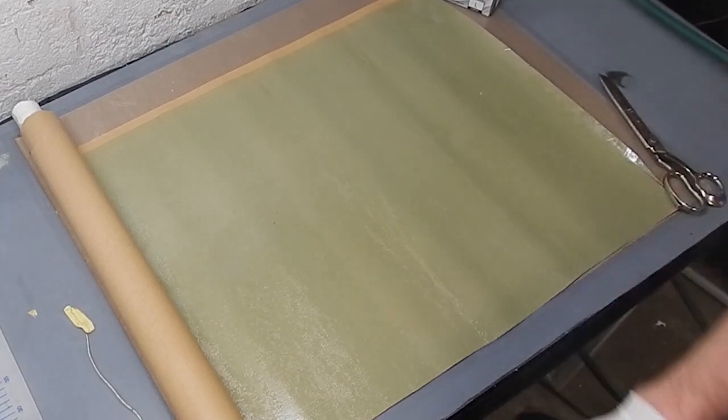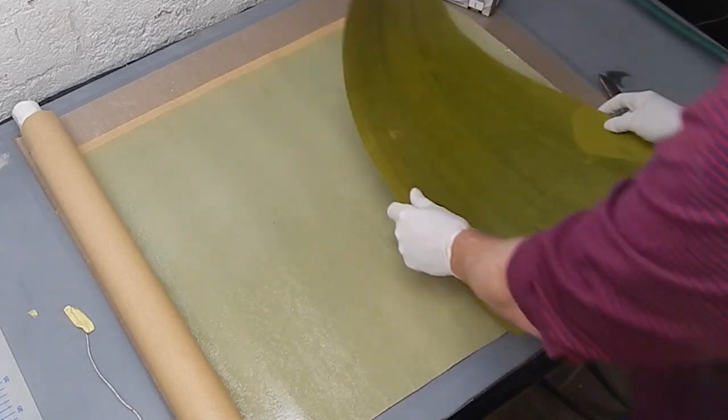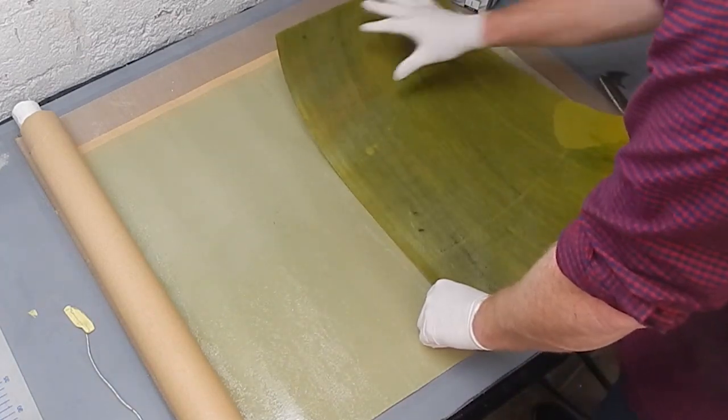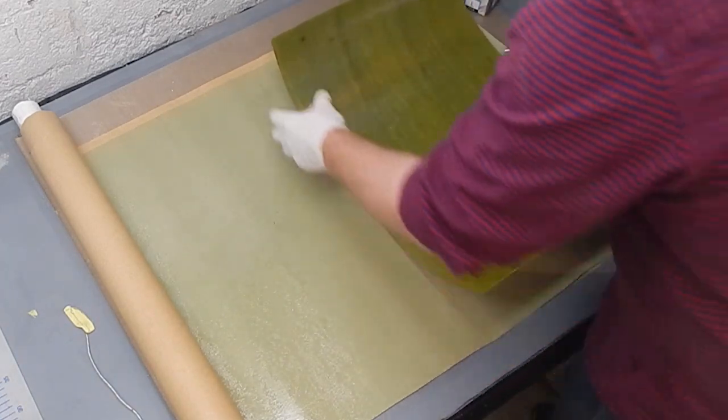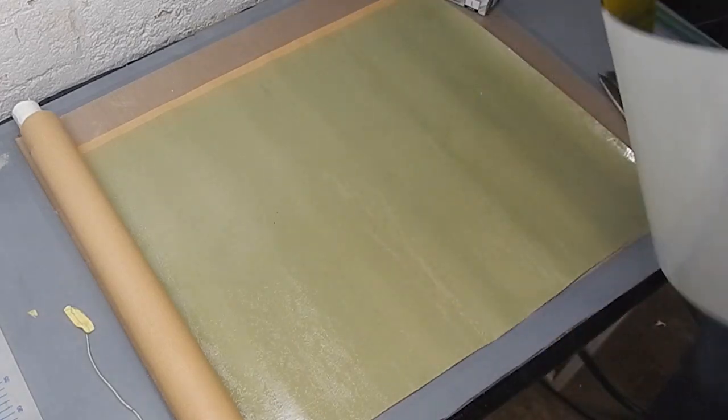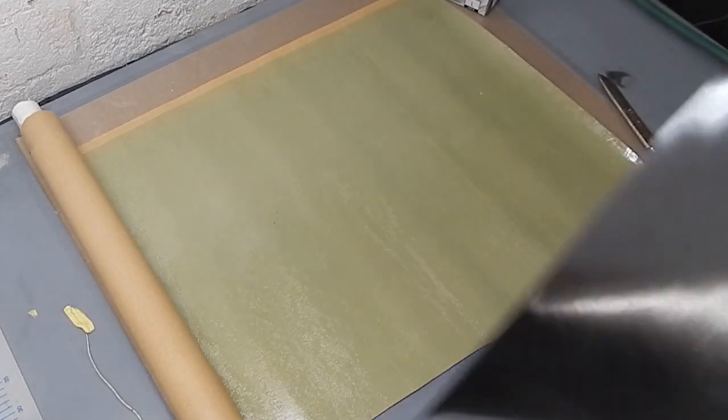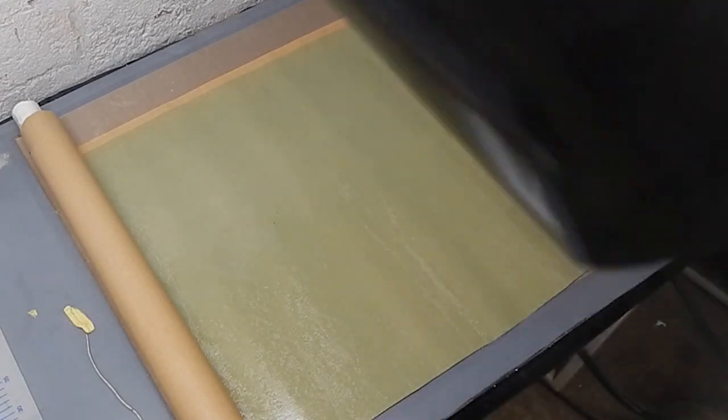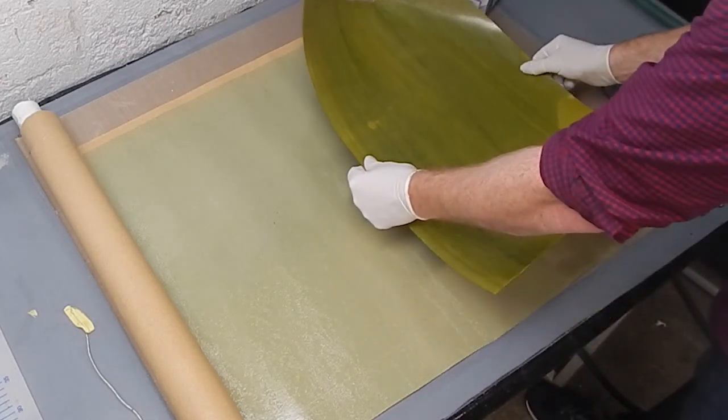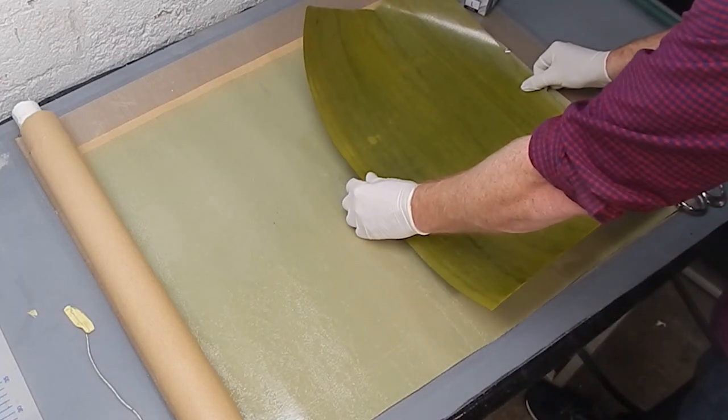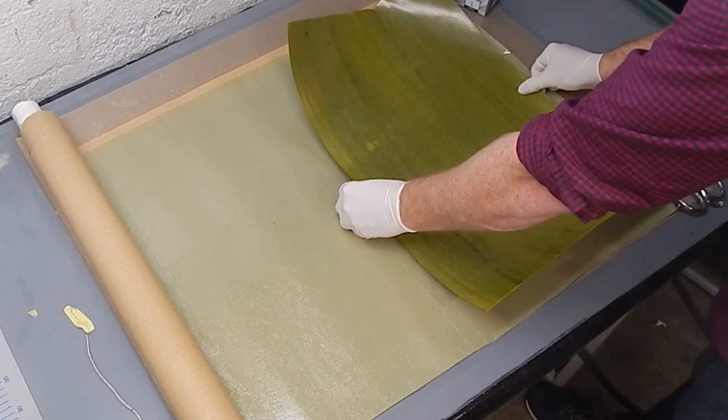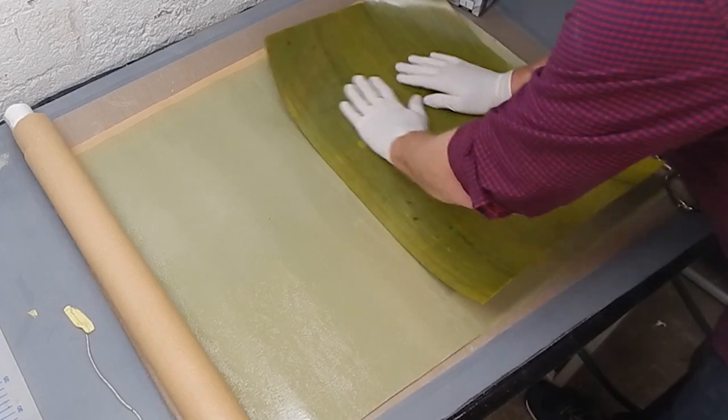This is a really easy way to apply glue film without having to worry about pressing it down into the cells of the honeycomb, and it gets most of the air out of the interface between the glue film and the carbon. Just so it sticks better, nice fillets between the honeycomb cells and the skins.